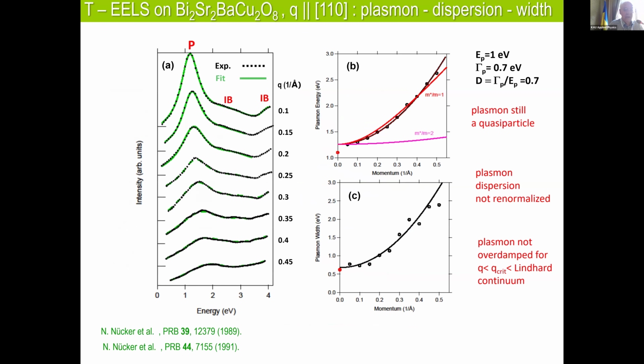Now here I show these data again with a new evaluation in terms of a two-Lorentz model. So the first excitation is a plasmon, and then we have an interband transition, and we look at the dispersion, which is shown here by these black dots. And when we do an RPA calculation with an effective mass of 1, then we get rather good agreement. But when we do the same calculation with an effective mass of 2, which we get, for example, from ARPES, we see a strong renormalization. So this indicates that the plasmon dispersion is not renormalized by correlation effects.